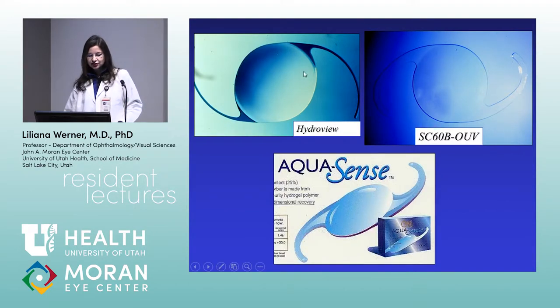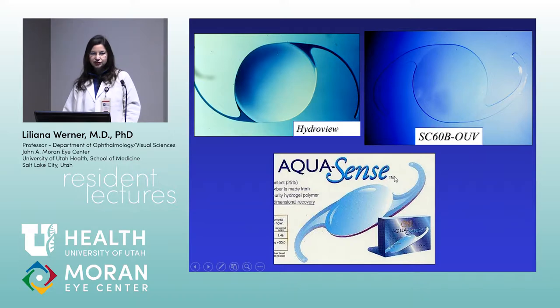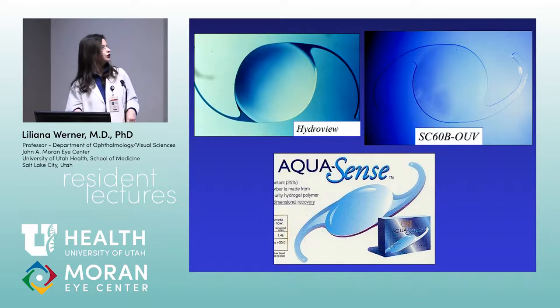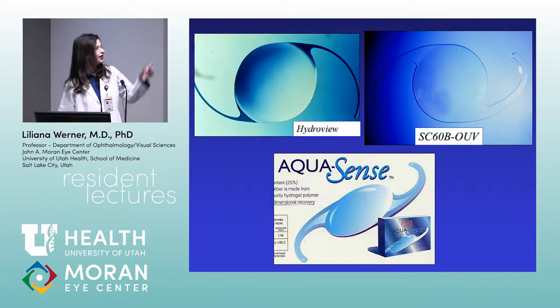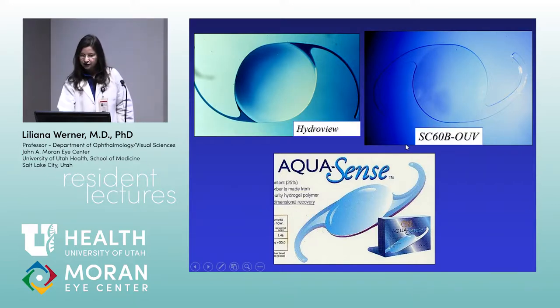To diagnose calcification, you can perform histochemical stains for calcium: the alizarin red stain directly colors calcium deposits red. You can also section the lens and stain using the von Kossa method, where calcium deposits appear black. Scanning electron microscopy at very high magnification, combined with energy dispersive X-ray spectroscopy (EDS), identifies elemental composition — producing peaks that confirm the deposits are made of calcium and phosphate. With the Hydroview, deposits were mostly on the surface; with other designs, calcification was within the substance of the lens.